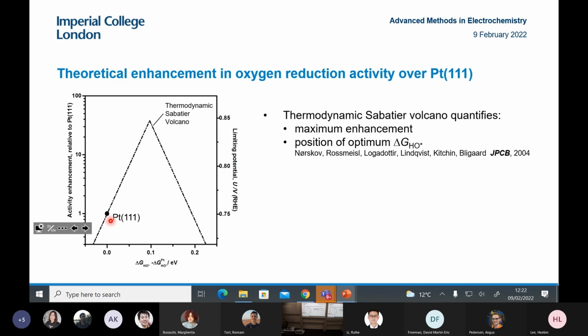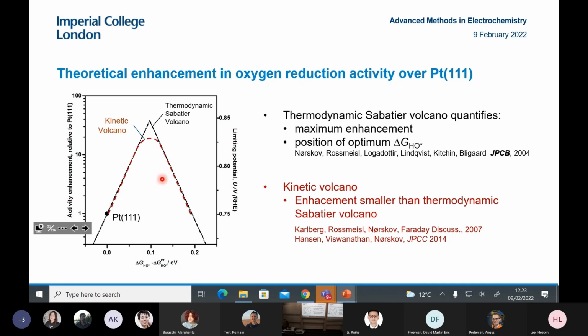So just to recap what we'd expect to see, this is zooming in at the peak of the volcano, this is activity relative to platinum 111. So if you weaken the binding to OH, we should see improvements in activity. And if you go too far, it's less active. Usually you can do this in two ways. You can either just look at the thermodynamic volcano. This is predicting what happens if there are no additional kinetic barriers, and purely based on thermodynamics, you'd expect to see a maximum of about 40 times improvement over platinum 111. But if you take into account full reaction kinetics, usually the enhancement's a bit lower. But this red trend is what we'd expect to see from experiments. This is what we want to set out and prove.